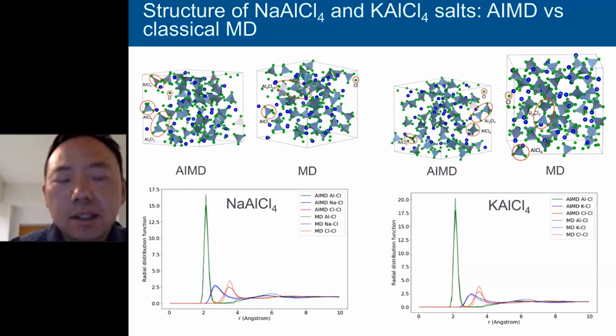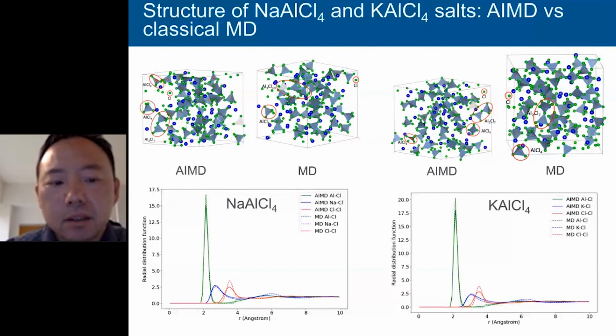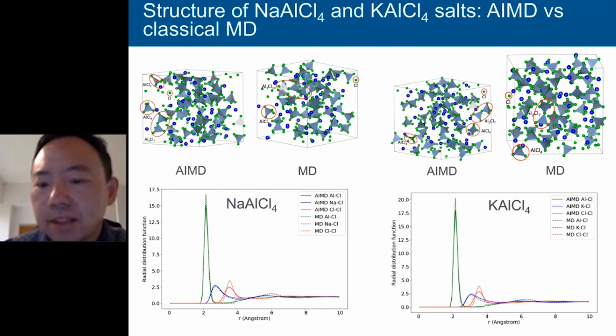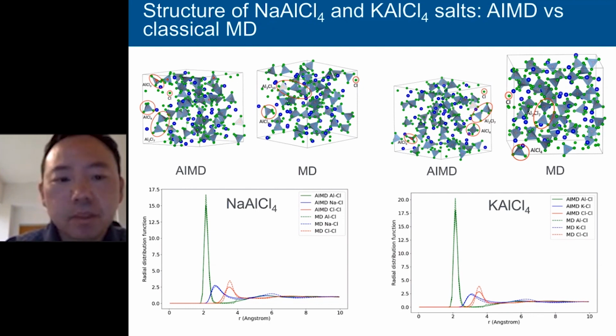Now we go to the more complicated mixtures between the sodium chloride and the aluminum chloride systems. The first 2 figures on the left show the results for the mixture of sodium chloride and aluminum chloride, and the right for the potassium chloride and the aluminum chloride. If you look closely at the 2 figures, you can see that in the AIMD simulations, there are lots of monomers, like aluminum chloride 3 monomers, in the liquid state. Due to the limitation of the model, the MD simulation will never favor this kind of monomer structure.